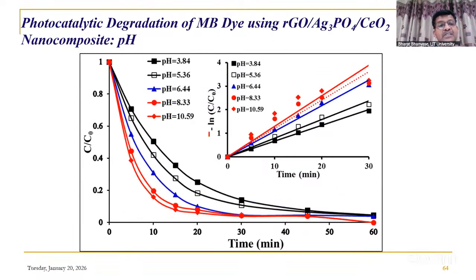At different pH, this study was carried out, and it is observed that in basic pH, the degradation rate is very high, and at the end of 1 hour, almost more than 95% degradation was observed.